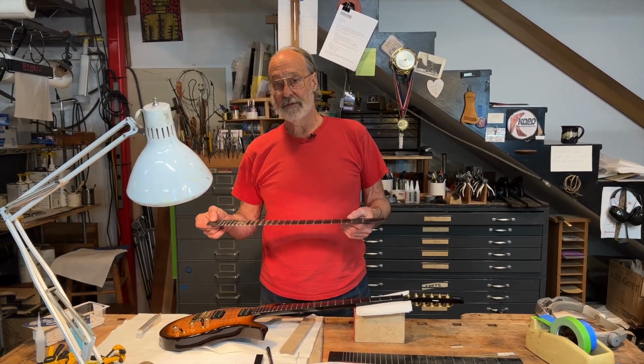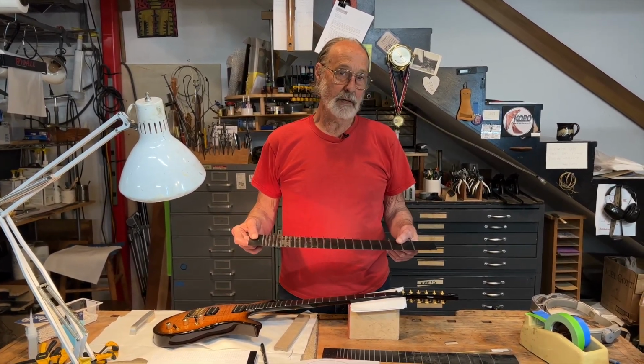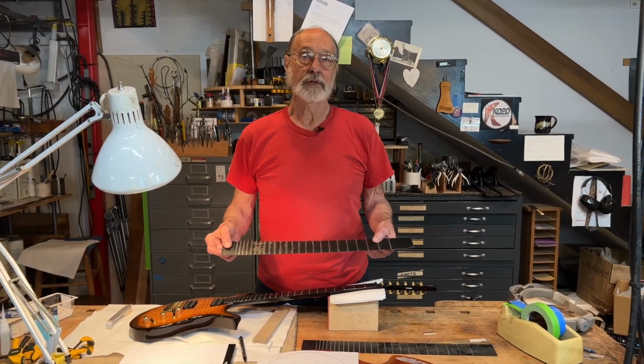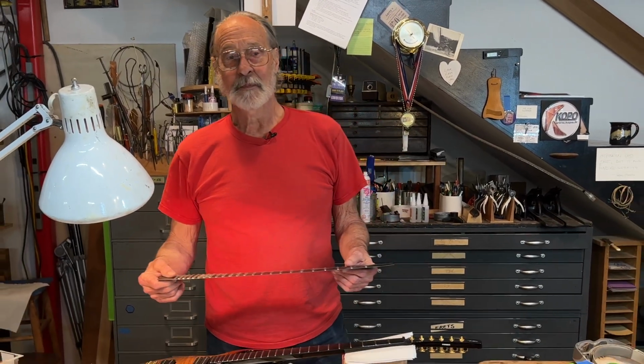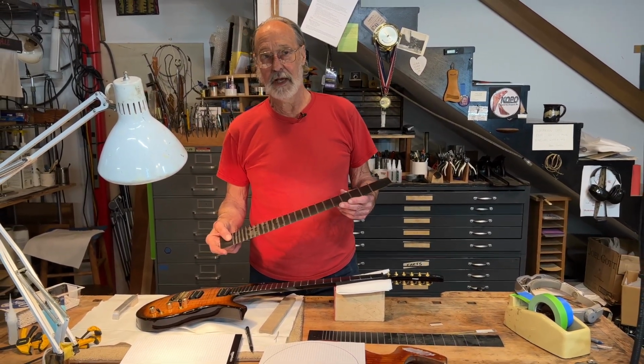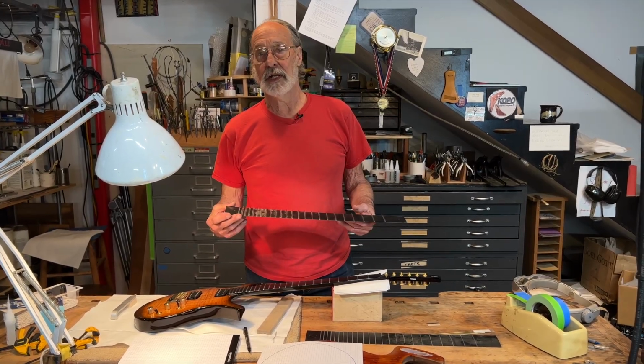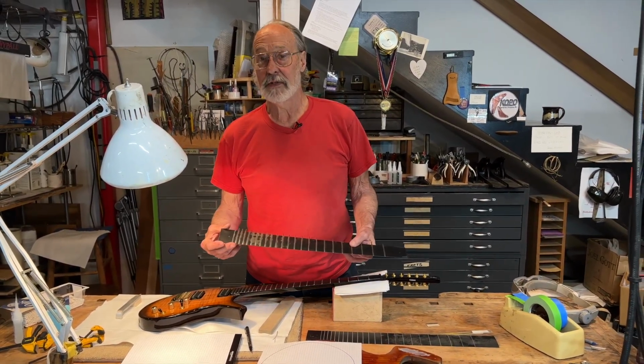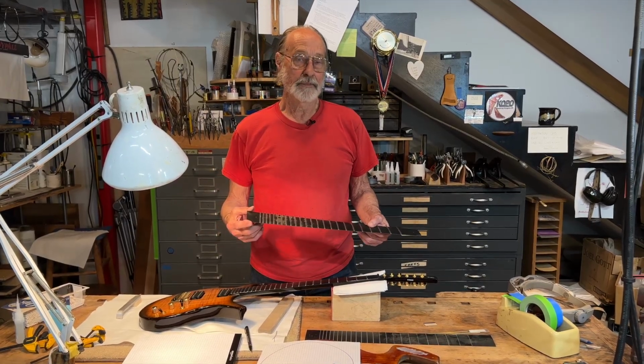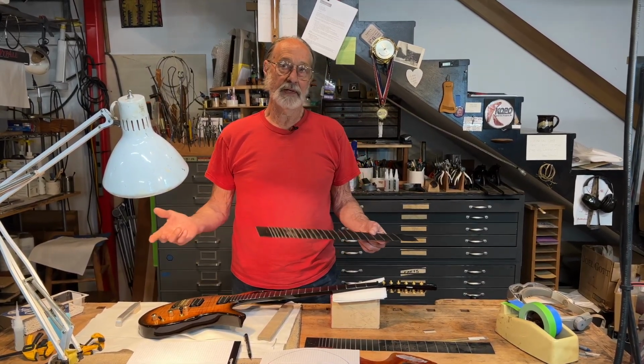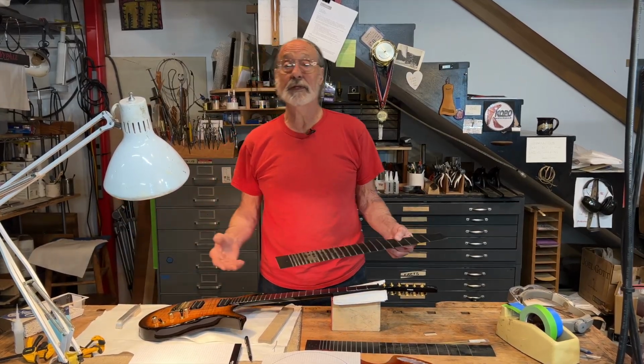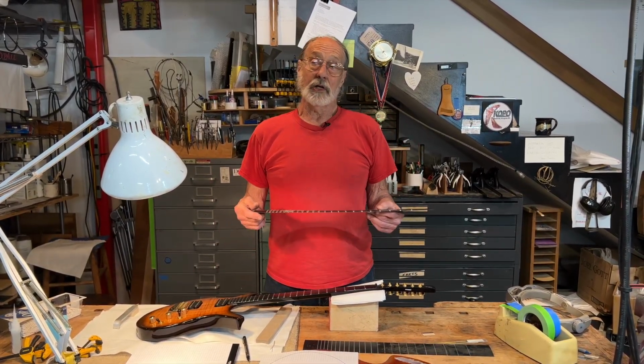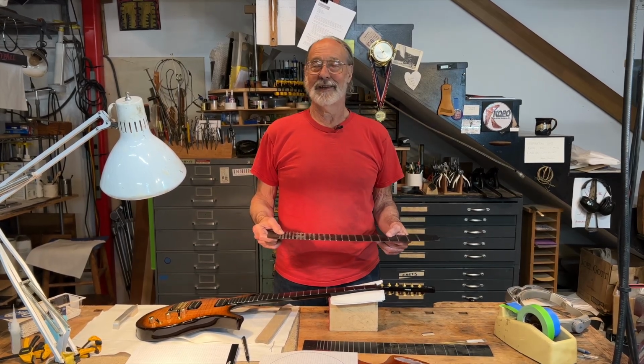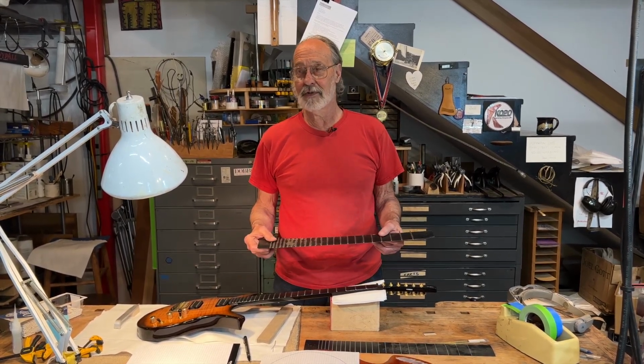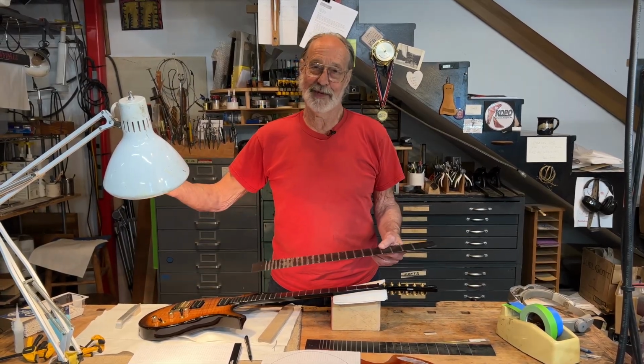In other words, if the frets were able to stay on through the sawing operation, we knew they would stay on the guitar. When we reordered adhesive after we'd finished the first batch, we started having adhesion issues. And I called up the company and I said, any chance that the batch of adhesive that we just got is out of spec? And they said, well, send us some. So we sent it back. They tested it and they said, no, it meets our specification. So it turned out that the first batch of adhesive that we got to test and to make the first bunch of guitars far exceeded their specification.